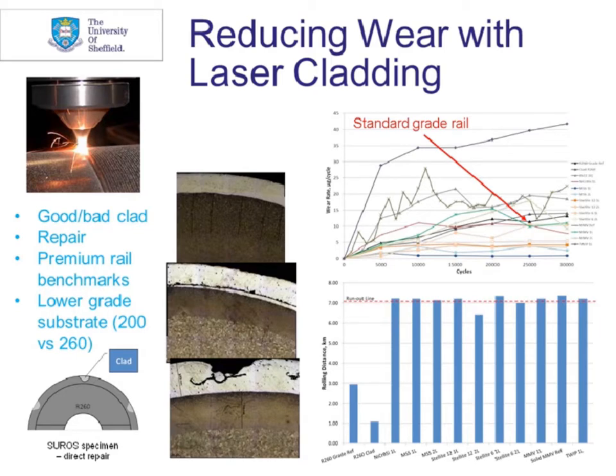And one area we've looked at in Sheffield now for a number of years for reducing wear of rail is laser cladding. So this is where you're applying a layer of premium material to the rail that's very hard and durable. And it's applied by focusing a laser onto the rail material and then feeding in the premium material as powder around the laser beam. So you have this little melt pool mixture of the rail material and then the premium material feeding in. And that gives you a very well bonded layer on the outside of the rail.